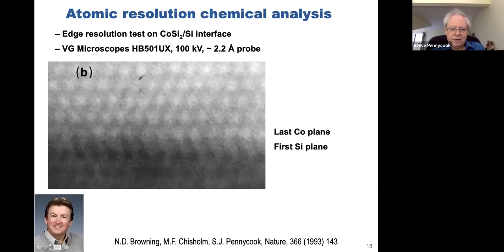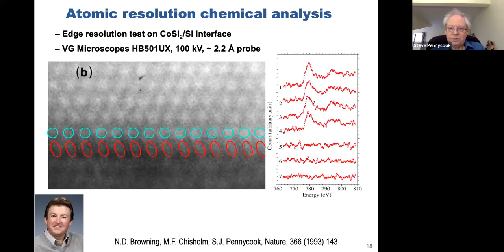Well, oh yes, and Nigel Browning, not to forget Nigel, came over to try atomic resolution energy loss spectroscopy. And this was a beautiful sample provided by Matt Chisholm, cobalt silicide, epitaxial on silicon. And although the image is horrible by today's standards, you can definitely see that it is an abrupt interface. And if you do the EELS, you see the cobalt edge does disappear across from this plane to this plane, which is about 2.7 angstroms, and we had a 2 angstrom probe. So that looked good.